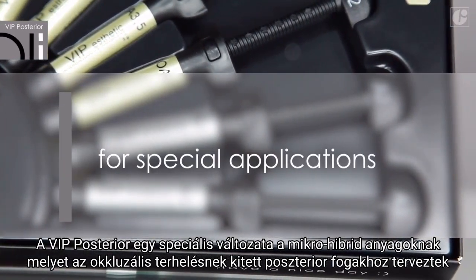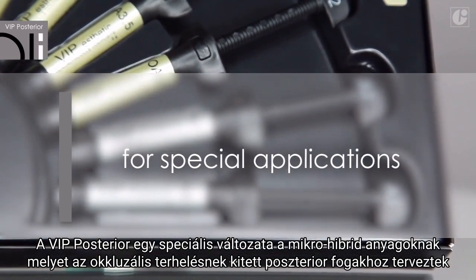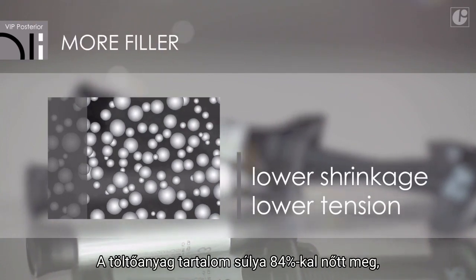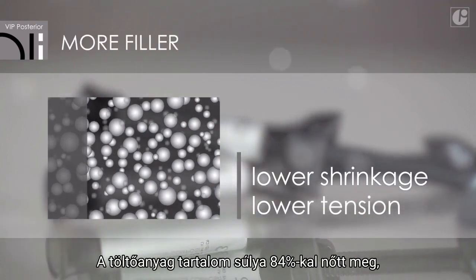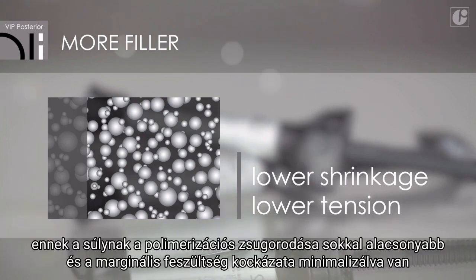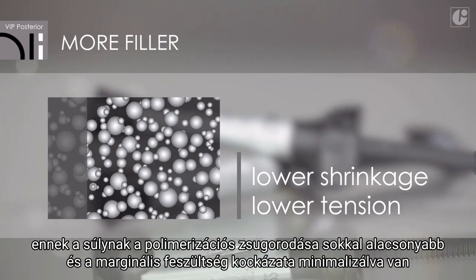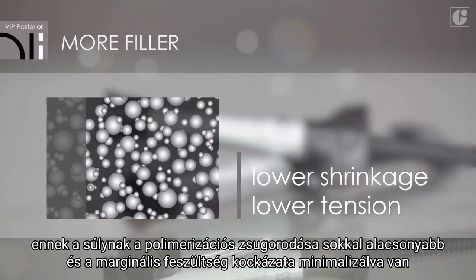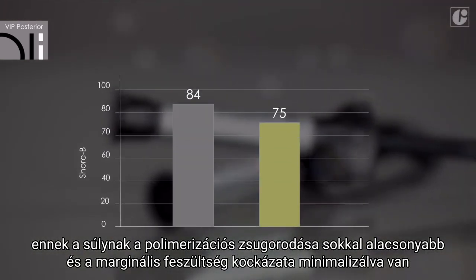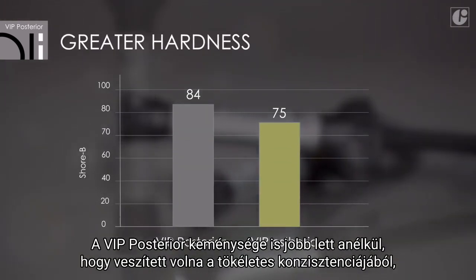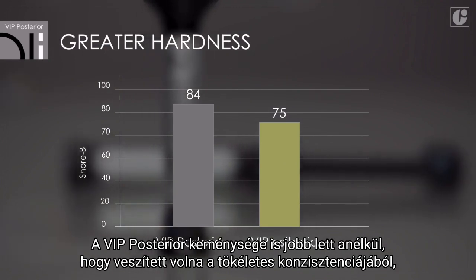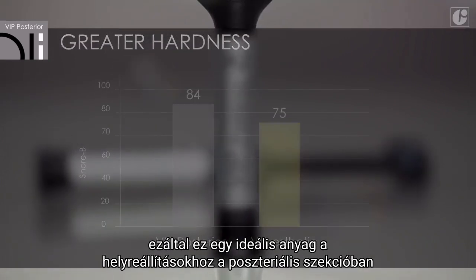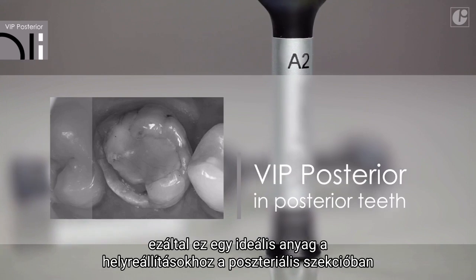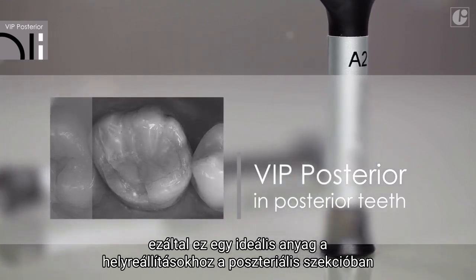VIP Posterior is a special version of the microhybrid material designed for posterior teeth exposed to occlusal loads. The filler content has been increased to 84% by weight. This way, polymerization shrinkage is much lower and the risk of marginal tension is minimized. VIP Posterior also gained on hardness without losing its perfect consistency. Therefore, it is an ideal material for restorations in the posterior section.